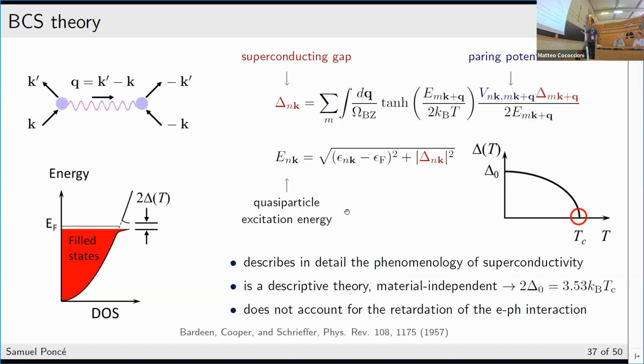Okay, so you can see that here you have this expression that describes the superconducting band gap as a function of temperature. This is the value at zero Kelvin, the superconducting band gap at 0 Kelvin. And if you increase temperature, basically the superconducting band gap goes to 0. And when it reaches 0, this is the critical temperature at which you lose the superconductivity. So it works relatively well.